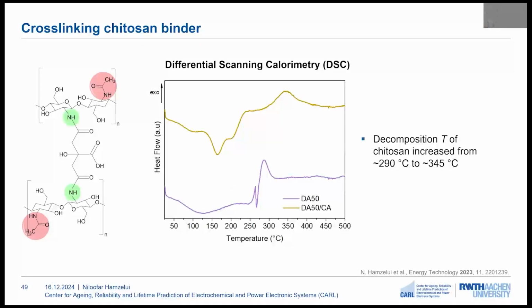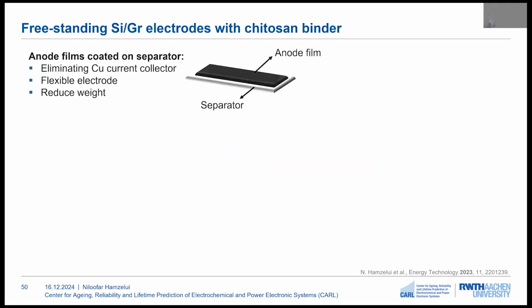Also, the thermal properties of the binders were investigated before and after cross-linking with differential scanning calorimetry. It was observed that the decomposition temperature of the chitosan was also increased after cross-linking with citric acid. As I mentioned before, the chitosan binder showed a good cohesion of the film. So this brings the idea of producing so-called freestanding electrodes to eliminate the use of a copper current collector, to reduce the weight and increase the flexibility of the electrodes. Therefore, the anodes were directly coated on top of a separator.